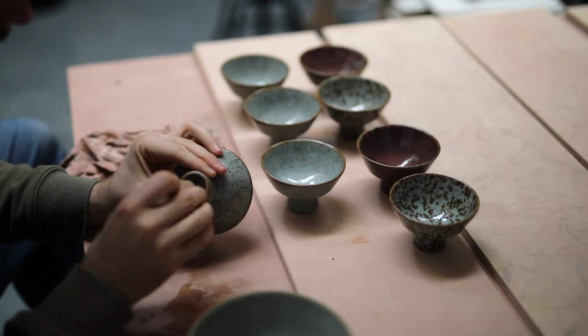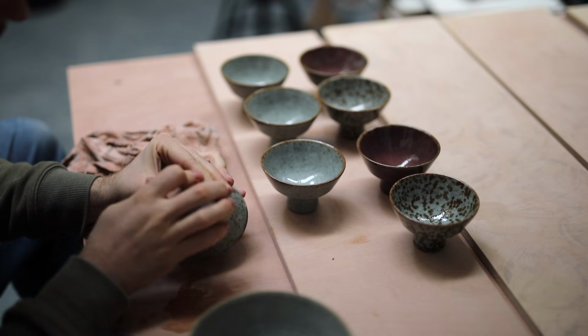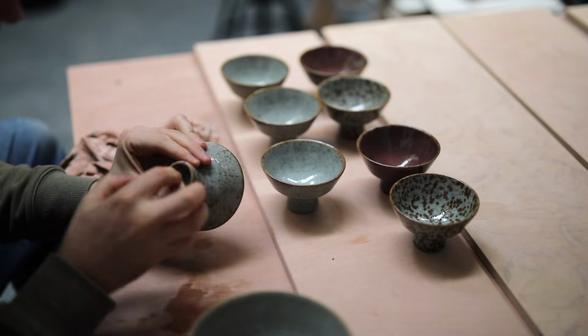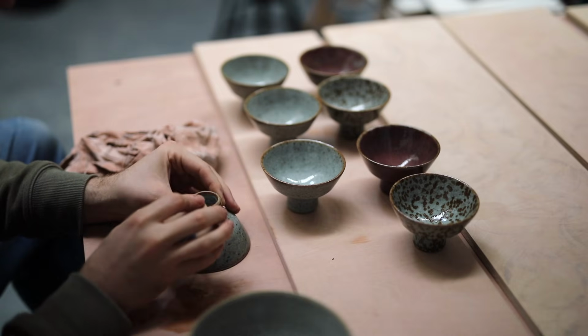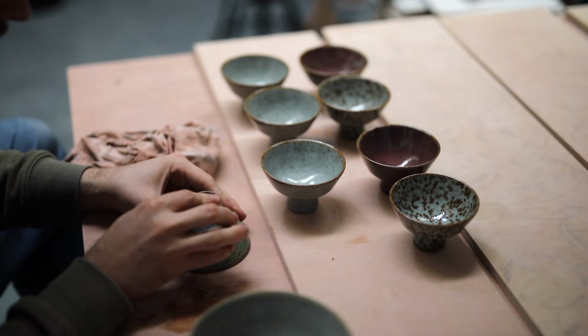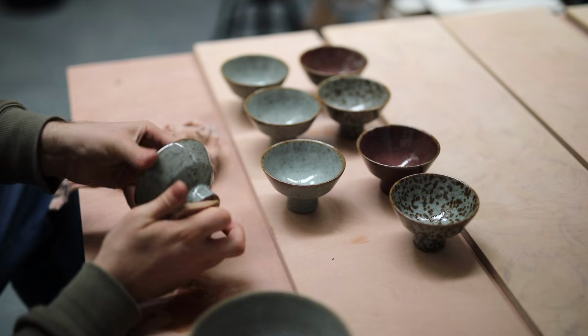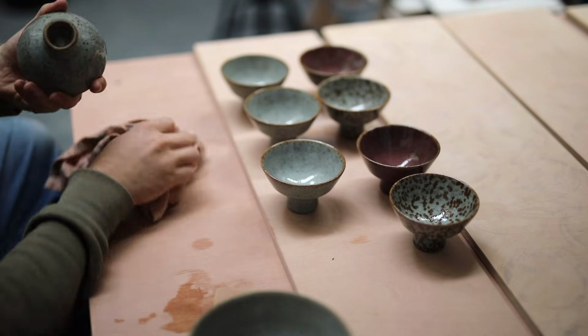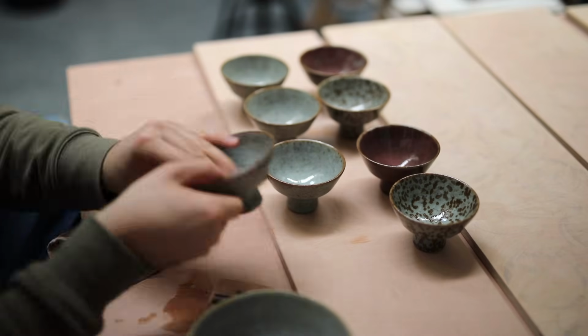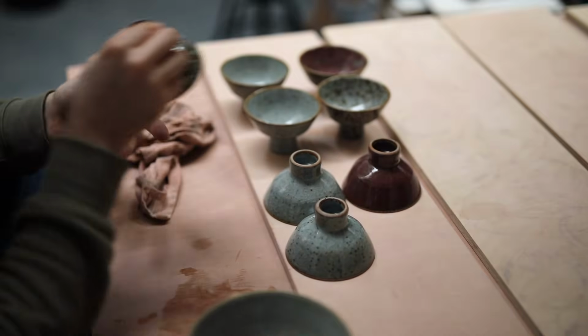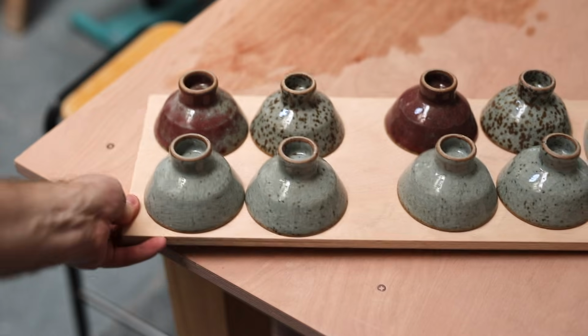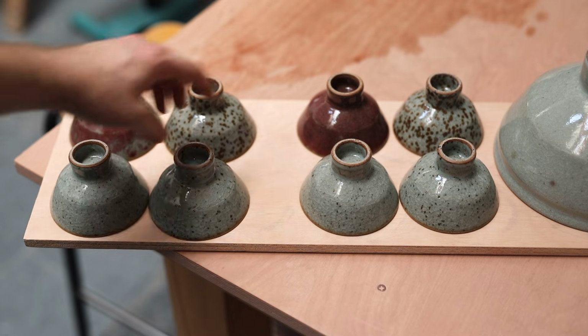Before I show you these in much greater detail, both as standalone pieces and with some macro shots, the next thing I have to do is sand the bottoms clean on each of these. The obsidian piece especially had some sharper shards of glass on the base. Equally the stoneware, which only contains 10% grog, despite being burnished to a glassy smoothness at the leather hard stage, becomes quite rough and coarse again as the stoneware shrinks around the pre-fired particles of ceramic the body contains.